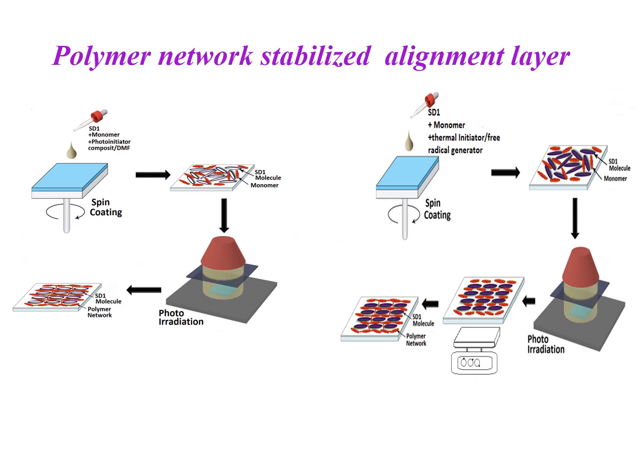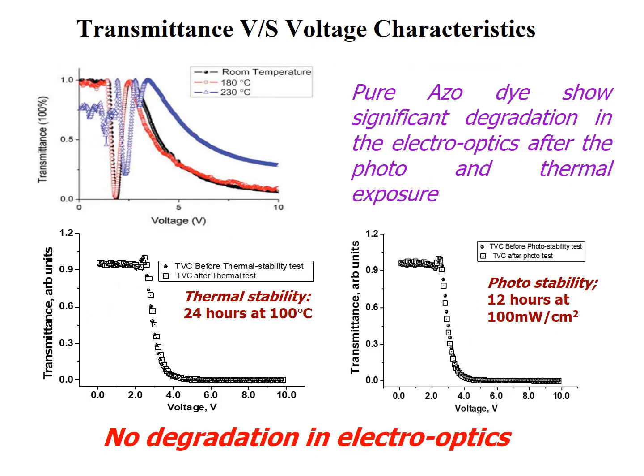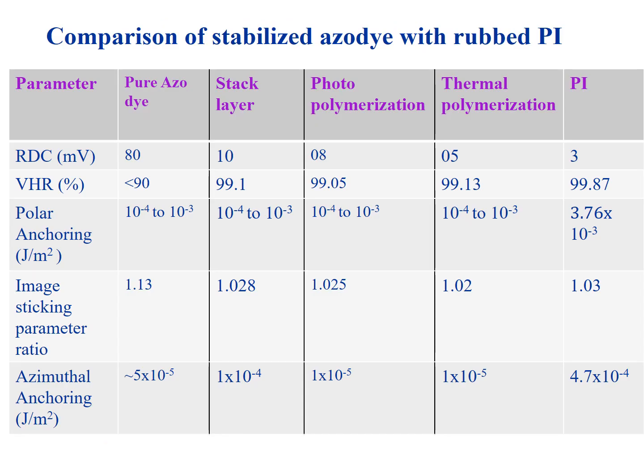If you would like to stabilize the liquid crystal alignment, you can add a liquid crystal monomer and then polymerize it, and the azo dye cannot move inside the polymer net. You can polymerize it using a photoinitiator or thermoinitiator. After stabilization, you will have high thermal stability, 24 hours at 100 degrees C, and high photostability for UV light, 12 hours at 100 milliwatts per centimeter squared. So here is a comparison table: the number of ions on the surface and in the bulk, anchoring energy, and image sticking parameters are comparable with the usual rubbing technology, or sometimes better.